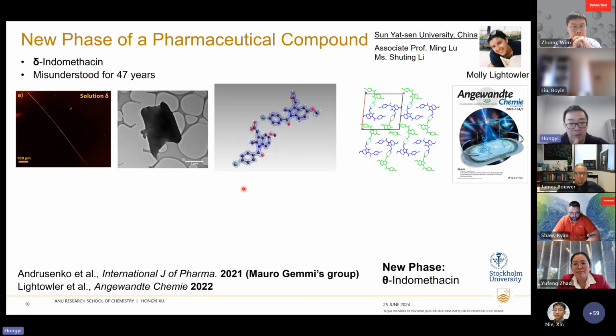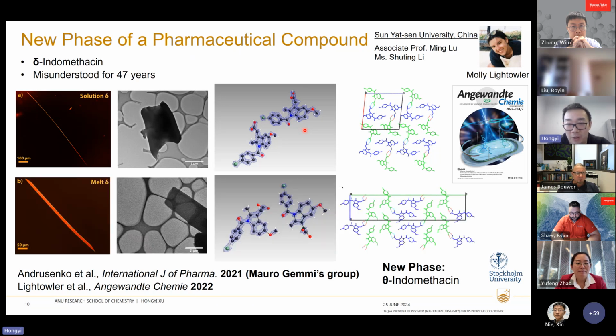So what happened is we took the solution-based crystal first and solved the structure, and around the same time, Mauro Gemmi's group in Italy solved the structure of the same polymorph. At the same time, Molly was also working with the crystal polymorph grown by melt crystallization, believing it to be the same form. And then she got a very, very different unit cell from this crystal. And then we realized that there are probably two different polymorphs.